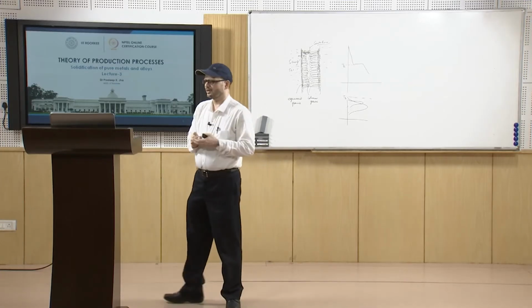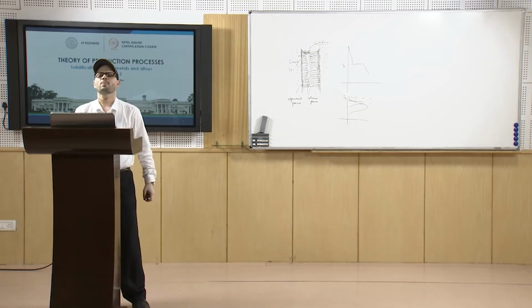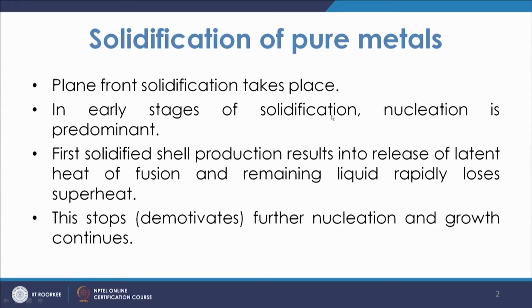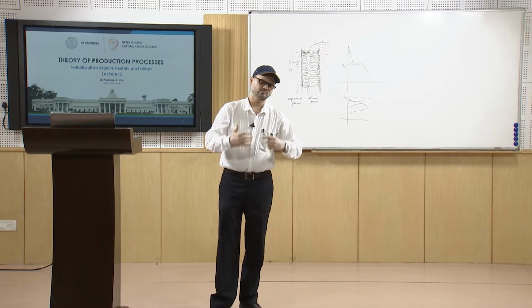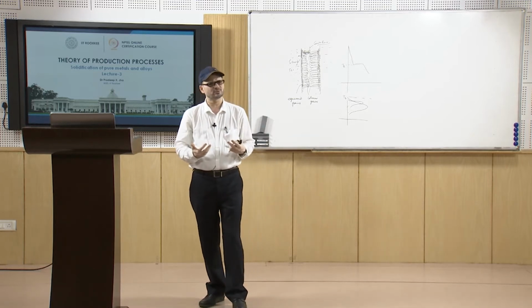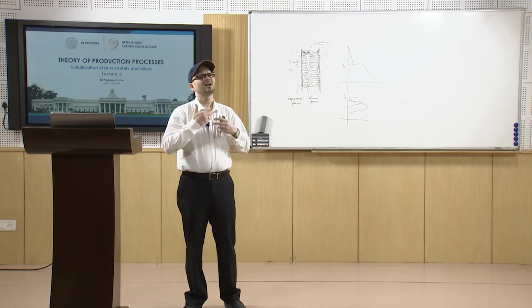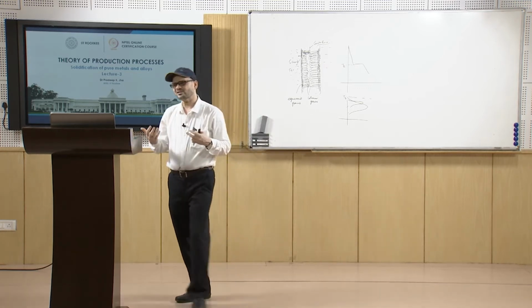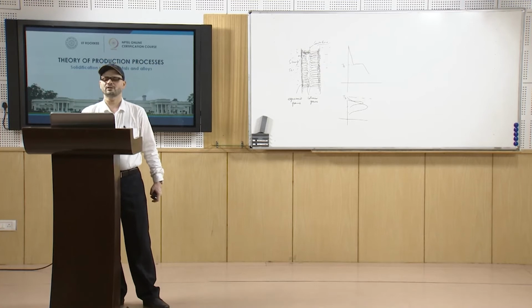What we see in our slide is that in the early stages of solidification the nucleation will be predominant, and the first solidified cell production results in release of latent heat of fusion, and the remaining liquid rapidly loses the superheat. Since it loses its superheat, the chances of further nucleation stop and the chances of growth predominate over nucleation, and that is how the solidification takes place.